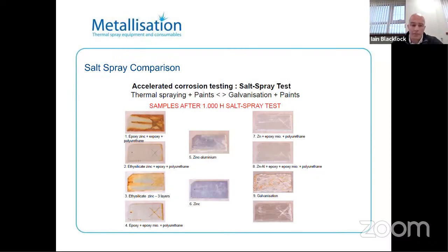There's a few salt spray comparisons here. On the left, generally you've got paint coating, so you can see where you've done the scratch test. You can see rust is forming. The two central ones are a zinc aluminium and zinc coated samples, all after 1,000 hours salt spray. And then on the side, we've got a galvanized sample plate, as well as some duplex coatings using zinc and paint coatings on top. So you can see the difference in the metal sprayed coatings compared to just the paint coatings. And this is the big benefit that this brings to various industries globally.